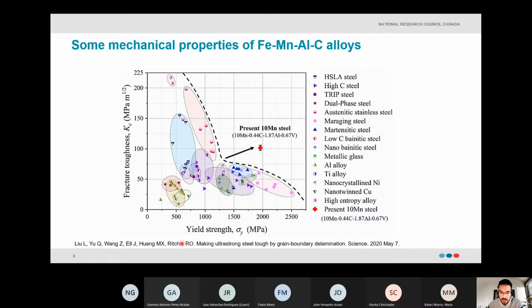This image was taken from this research. Basically, they developed a new manganese aluminum alloy. And we can see here how the properties as a function of fracture toughness and yield strength compare to other families. For instance, austenitic stainless steel is this pink circle here. The austenitic steels have a really good fracture toughness, but the yield strength is below 1 gigapascal, but it's pretty good anyway. When we compare with high entropy alloys, we can see that this is the new trend in physical metallurgy, the high entropy alloys. The fracture toughness is really high, but the yield strength is still too low.